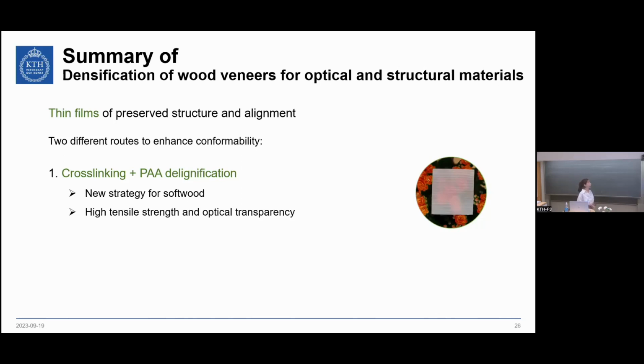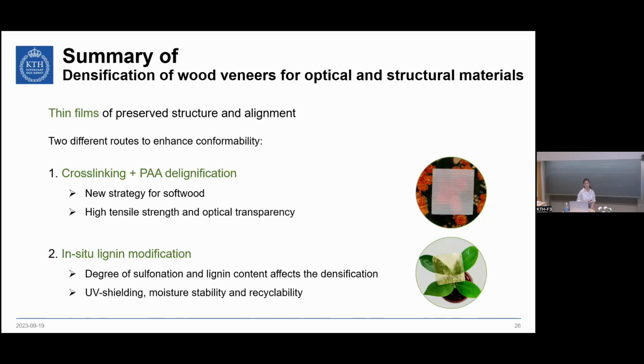The other thing is that we could also see how preserving the alignment is beneficial both from an optical as well as a mechanical perspective. In the second part, we see that if we preserve lignin, then it's important to tune the level of sulfonation as well as lignin content. And that preserving the lignin also endows the film with additional properties. In this case, it was UV shielding, moisture stability, as well as recyclability of the material.